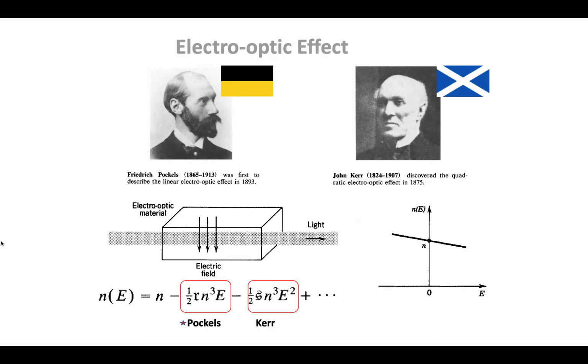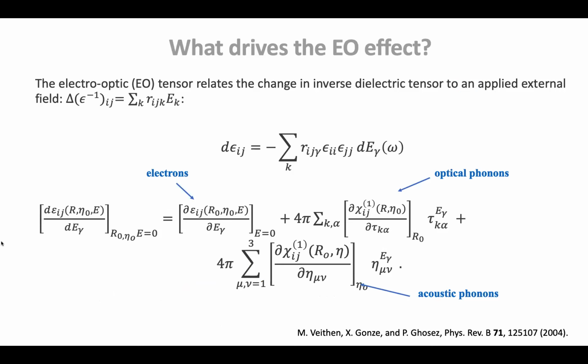And so why does it change? So here it's written in terms of the dielectric tensor, but it's the same thing as refractive index. The idea is if you apply electric field to a material, first of all, you tilt the band structure. So all of your transitions are now changed, and that's your Chi2, right? Chi1 doesn't depend on field, but Chi2 does. Nonlinear susceptibility, high frequency response, electron response.